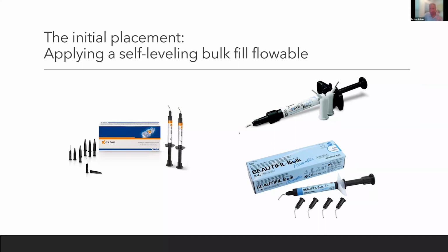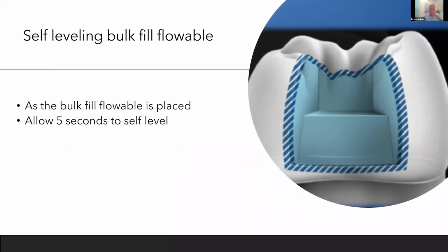So that's the first. How long are you going to cure? Again, based on depth, I would cure 20 to 30 seconds minimum. 10 seconds, you're not going to cure long enough. Why? Flowables take longer to cure because they're more filled with resin, so you're further from the light. You've got to cure longer. Again, 20 to 30 seconds.